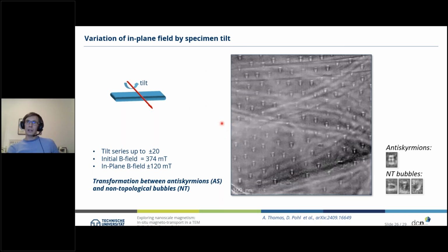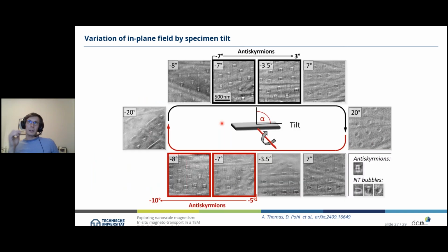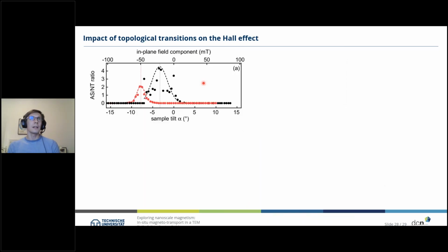And then we started to analyze all that data, all those 400 images, and found different scenarios where we started with anti-skyrmions, tilted towards higher tilt angles, where we lose the anti-skyrmions and go to non-topological bubbles, then tilt back towards the negative direction, coming back to an anti-skyrmion area for certain tilt angles, and then tilting back to the original tilt value. So we have the images, but at the same time, we can now analyze the images. And since it was not always possible to track the anti-skyrmions or the bubble features, we used here the ratio of the measured anti-skyrmions to non-topological bubbles, and can therefore nicely define areas where the anti-skyrmions pop up, in the forward tilt direction and the backward tilt direction.